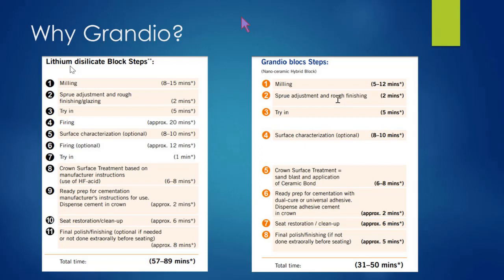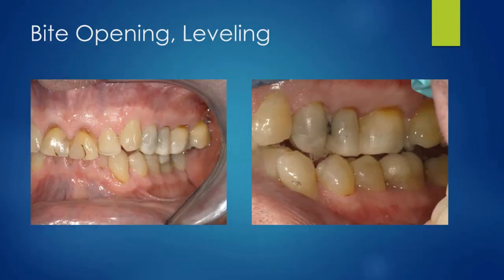But the other thing that's really important to understand is what happens once we've designed our restorative. In the case of a lithium disilicate material, we're looking at about 57 to 89 minutes total to get that thing out, bonded, and polished. Where in the case of Grandio block, because there's no secondary firing required for crystallization or for sintering, we can have these out in about 30 minutes or so. And it's very common for me to do one or two of these restorations within an hour and have the patient out of the office within an hour fully bonded. That is an incredibly profitable and fun way to practice dentistry.